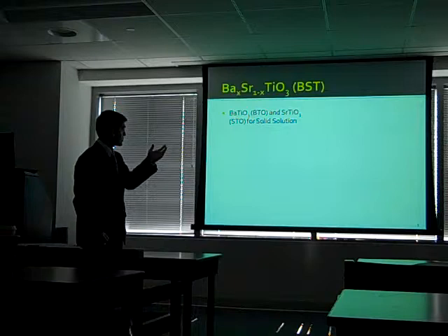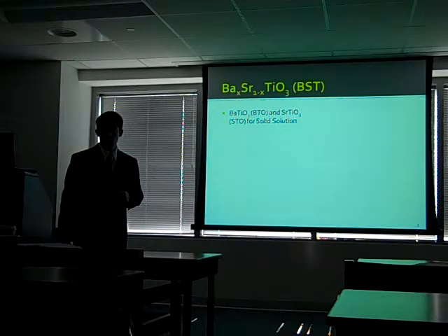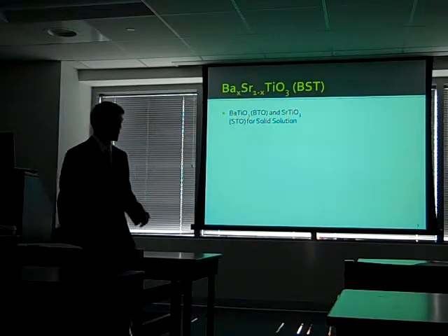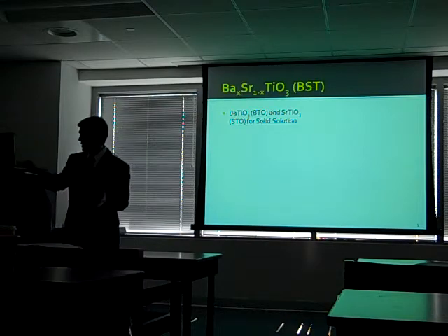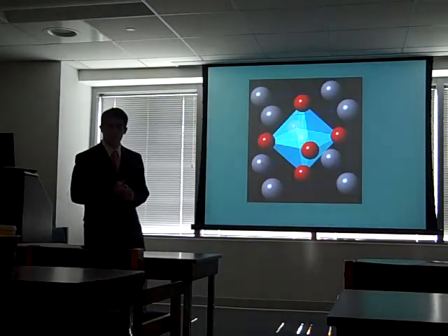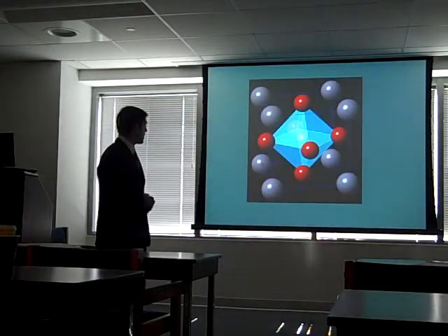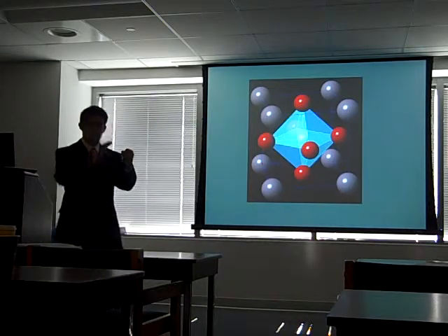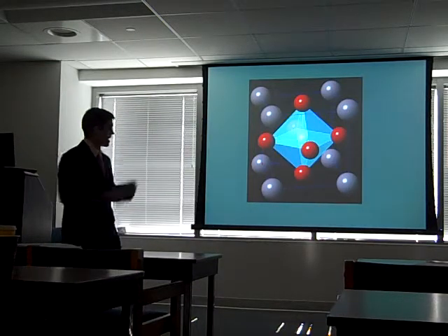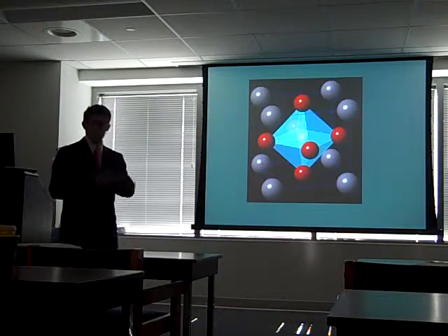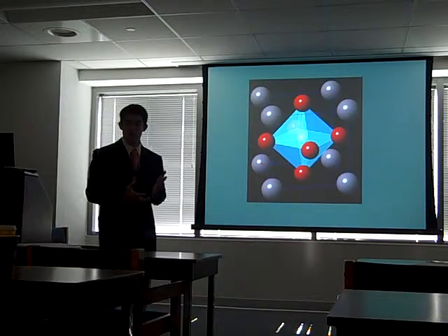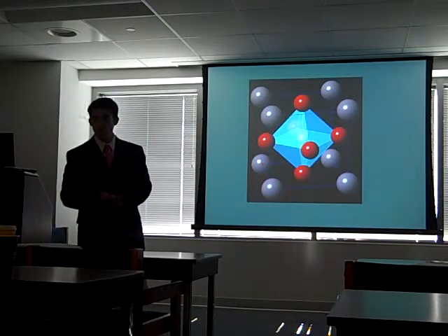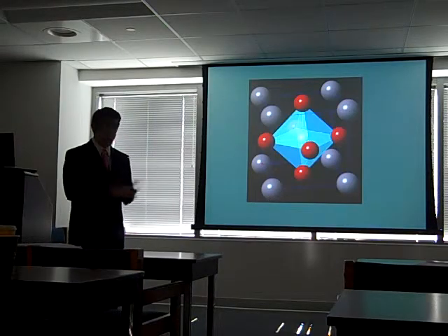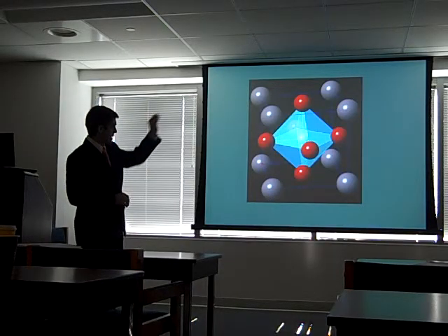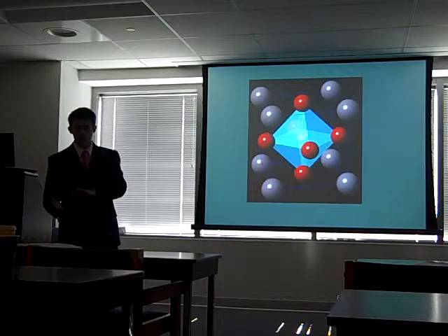properties, is barium strontium titanate. Barium strontium titanate, or BST, is a solid solution of barium titanate and strontium titanate. It packs itself in the cubic perovskite structure. There's a central titanium ion surrounded by an oxygen octahedron, and then at the corners are barium or strontium. So depending on your alloy percent, if you have 60% barium, 40% strontium in your BST alloy, then 60% of those at the corners will be barium ions, and 40% of them will be strontium.